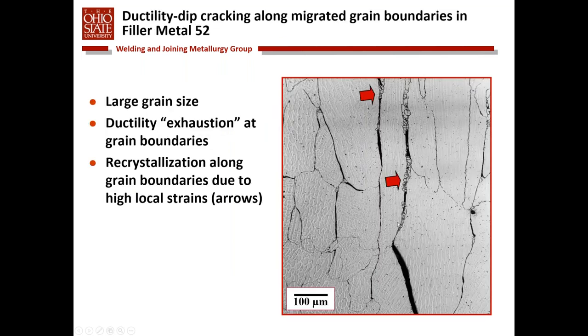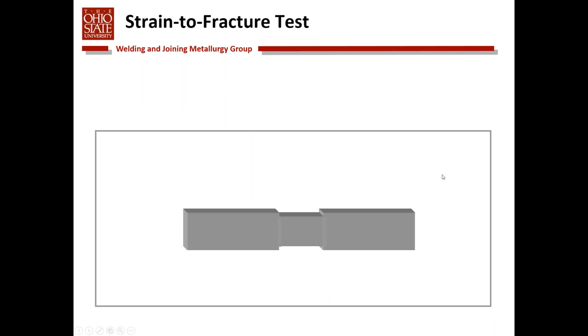This is what DDC looks like in some nickel-based weld metal. Cracking occurs along what we call migrated grain boundaries. Again, this is a pretty severe case, but this is in an early filler metal that was a high chromium filler metal that was developed for welding alloy 690. It has since been abandoned in most cases as a filler metal because of its susceptibility to ductility dip cracking.